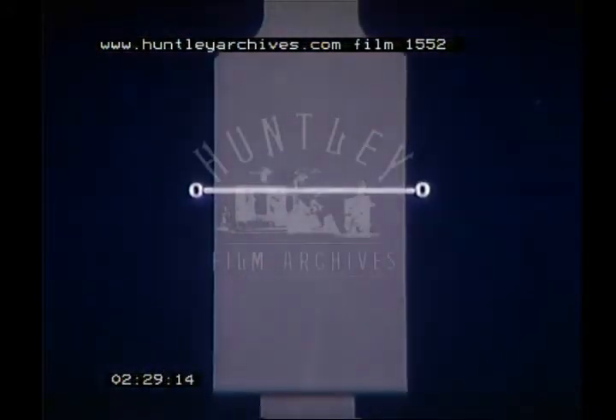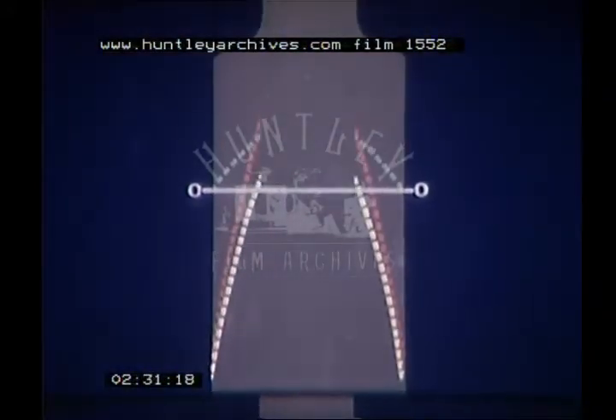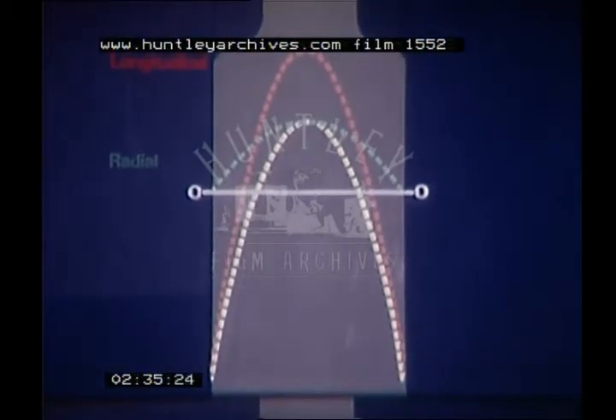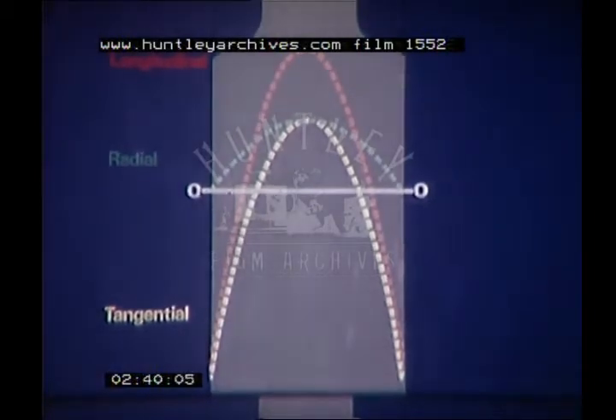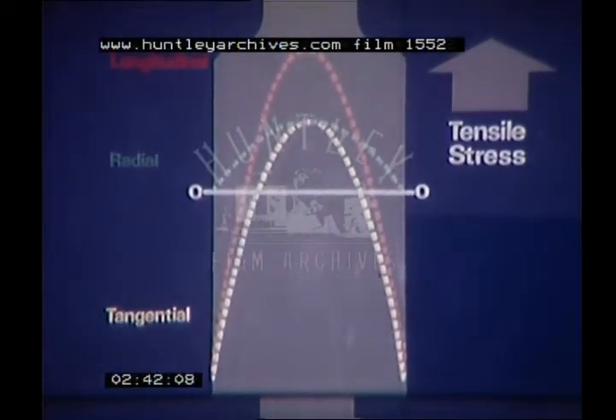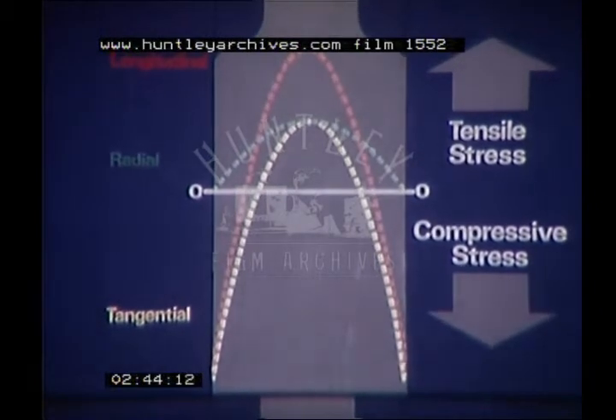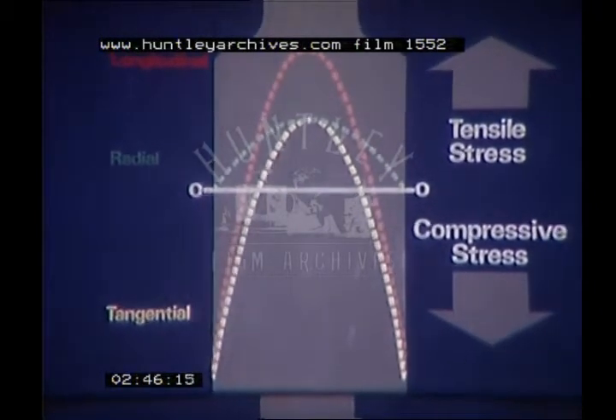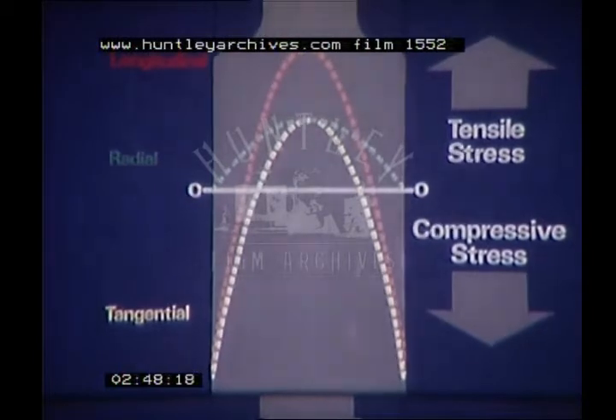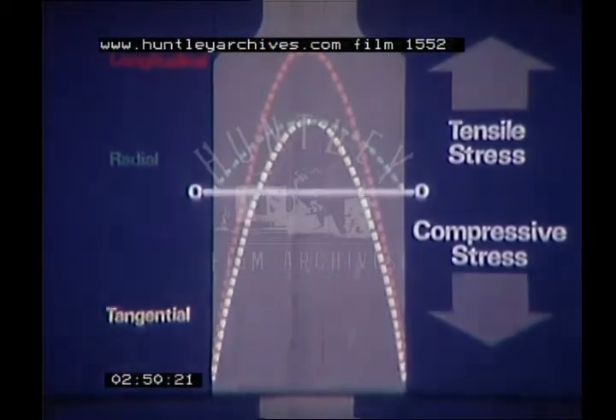When a solid piece of steel is heated to a uniform temperature and then water quenched, the outer layers cool very quickly, and as the inner layers cool, they do so against the restrictions imposed by the outer layers. Thus, a complicated triaxial stress system is set up. The magnitude of the stresses is very high, with tensile stresses in the region of 60 to 70 tons per square inch set up at the center of the roll.